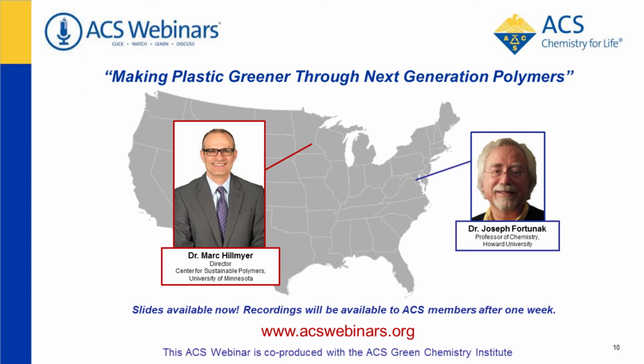Fengwan Yan wants to ask a bit about the processability of these polymers with respect to using them for extrusions and forming textiles and the like. That's a really important point. When you take these polymers, and in particular aliphatic polyesters that we focused our attention on, you have to get them from the beaker ultimately to a product, and that does take processes that in the polymer industry are largely melt, non-solvent based processes, which means then you have to heat above that highest melting or glass transition temperature and be able to, for example, extrude them or injection mold them.